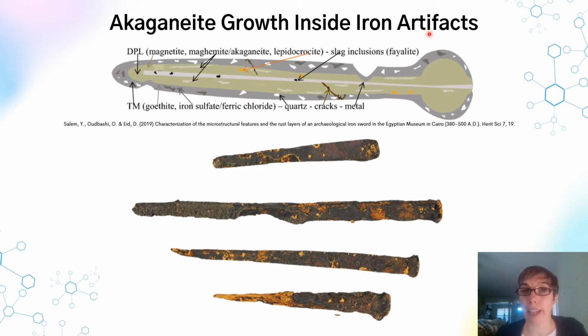And the problem with akaganeite, much like with nantokite and its reduction products essentially, is that it tends to form inside the iron artifact, usually at the border between the core metal and the beginning of the corrosion layers, resulting once again in a situation where you have a corrosion product growing in a space that is much too small for it, resulting in eruptions of material through the surface of the object. And in the case of wrought iron, like these nails you see here, which have a very specific, tiered grain structure, kind of like a tree, you can have whole layers that just separate and fall right off until there's very little of your artifact left.